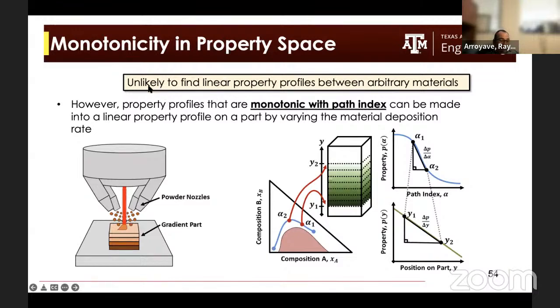Okay, so what we know is that it is unlikely to find these linear property profiles between arbitrary compositions. However, one thing that my former student Tanner Keir discovered was that if we ensure that the path in the composition space was monotonic in the property space, that is, if we ensure that the trajectory changed the properties only in one direction, so it always went down or up, we could then create any arbitrary linear or nonlinear profile of this property by just controlling the deposition rate.